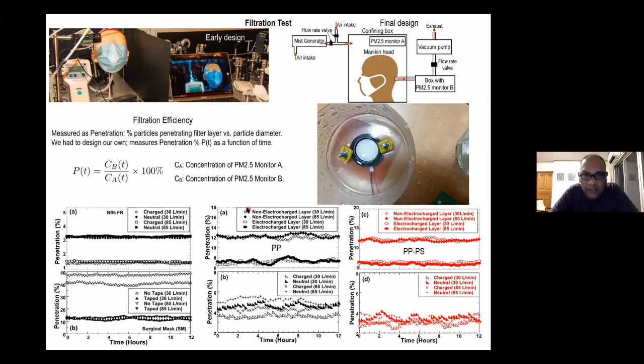So you see non-electrocharged layer measurements at 30 and 85 liters. They give me a measurement of about 12%. For these tests with the surgical mask, everything was done by taping it so that I don't get any interstitial gap. That's why I'm seeing 12% penetration. Without the electrocharged layer, I'm getting about 12% penetration. With the electrocharged layer, I get close to 7% or 8% penetration. So the electrocharged layer definitely makes a difference, but it is still higher than the N95 quality.